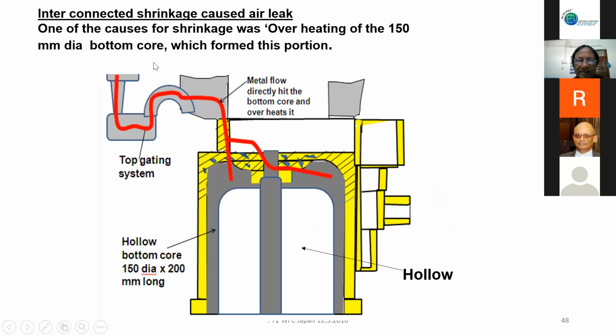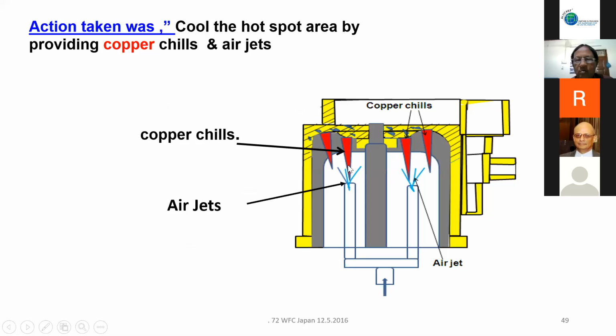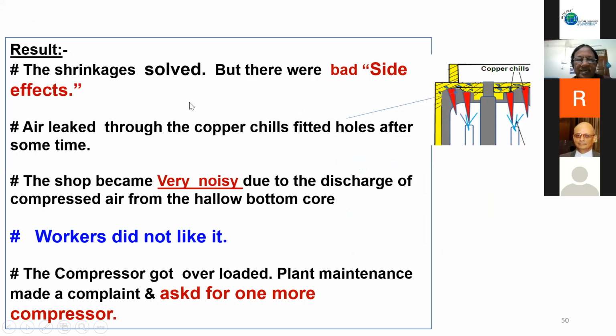Now the problem is, one of the causes for the shrinkage was overheating. There are so many causes, maybe lack of feeding, this and that. One of the causes we noticed is this goes up beyond 400 degrees centigrade. So what we planned is to go for some copper chills and cool the chills by air jet. It's a hollow core made of cast iron. We tried to cool it with air, and then we found the shrinkage was solved. But it has got so many side effects.